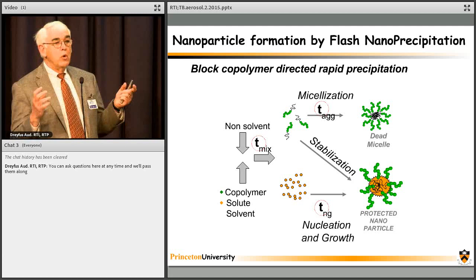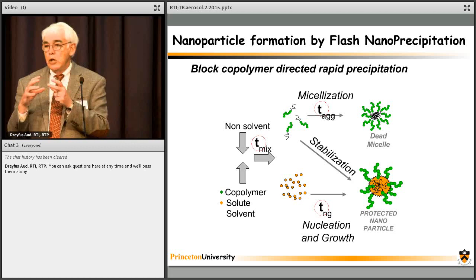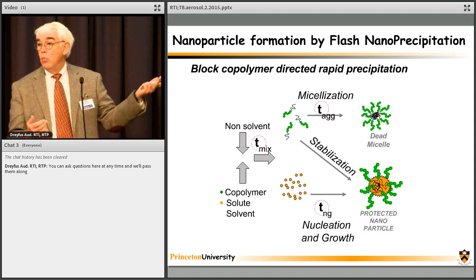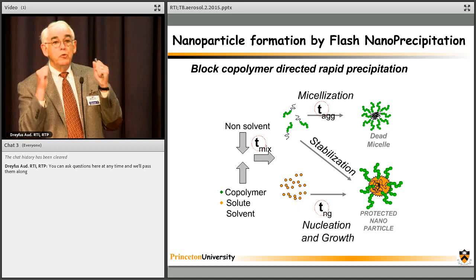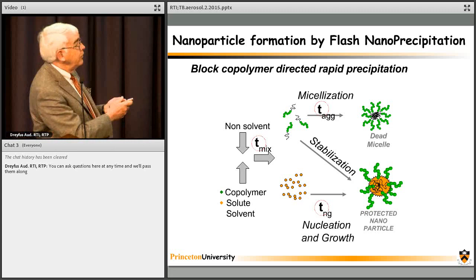So what we're doing is going from a system which is completely dissolved, and then in a millisecond and a half of the micro-mixing in this chamber, the system will go from being all the hydrophobic components happy to be dissolved to suddenly being in water, and they don't like being in water. They're diffusing, and they're so super-saturated that the first thing they hit, they stick to. Okay, and that's the key here. So we have the micromixing.